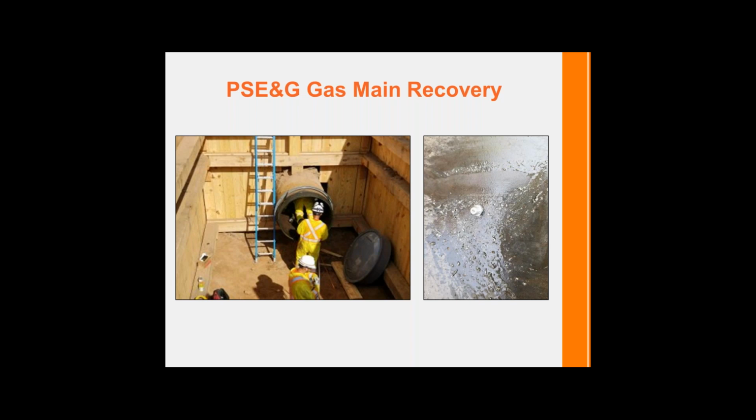They actually drilled through the steel pipe, tapped in the zerks, patched and repaired the pipe where the corrosion had occurred with an epoxy, basically to patch and repair to prevent some of the heavy infiltration so they could kind of fill the voids. And then they tapped the zerks in and injected our AV275 to the outside. Basically, they hit all the joints where the infiltration was occurring most heavily. The material locked the soils together on the outside, formed a barrier around the structure, and prevented the water from coming in so that they could actually put the liner inside that structure.